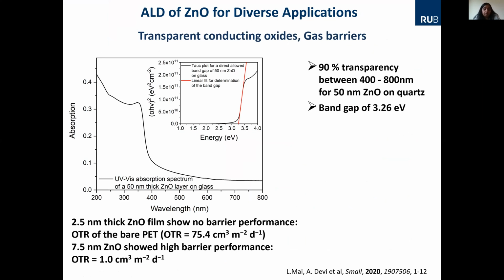Transparent conducting oxide. So that's one thing: can we look into the optical band gap? So we did some UV visible spectroscopy. You can see the absorption as a function of wavelength. So this is the Tauc plot, where from the absorption curve we can calculate the band gap. So for films of 50 nanometers, between 400 nanometers and 800 nanometers, we had a very high transparency.